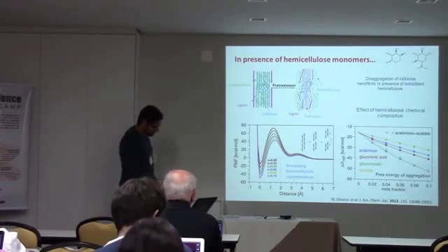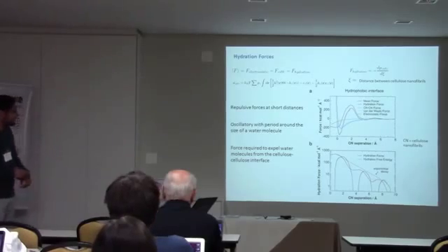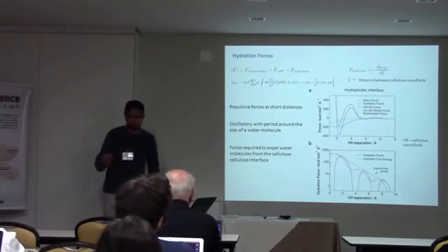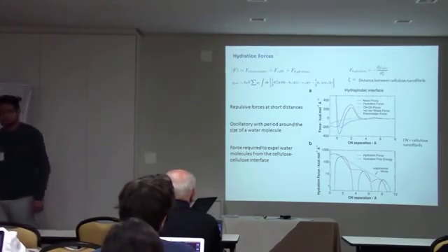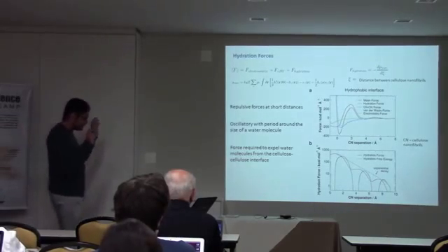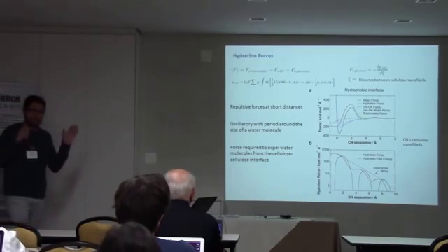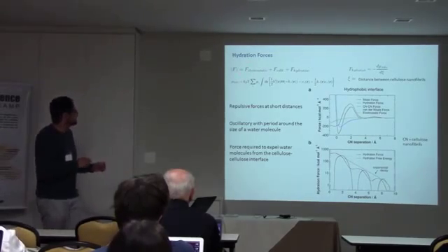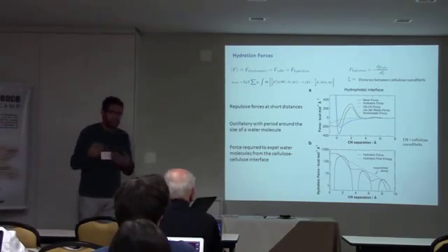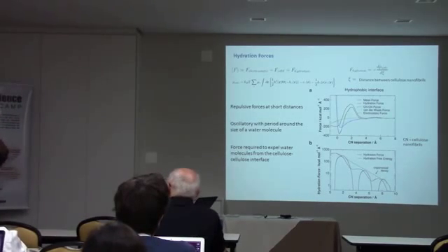And from this theory, instead of analyzing the free energy profile, we can also compute forces. And these are not only mechanical forces. For example, let's imagine we have two cellulose fibers, and these cellulose fibers will interact through electrostatic interaction. So you have an electrostatic component, you have a van der Waals component, and you have another component that's not mechanical. This is thermodynamic. This is a solvent effect, which comes from hydration.